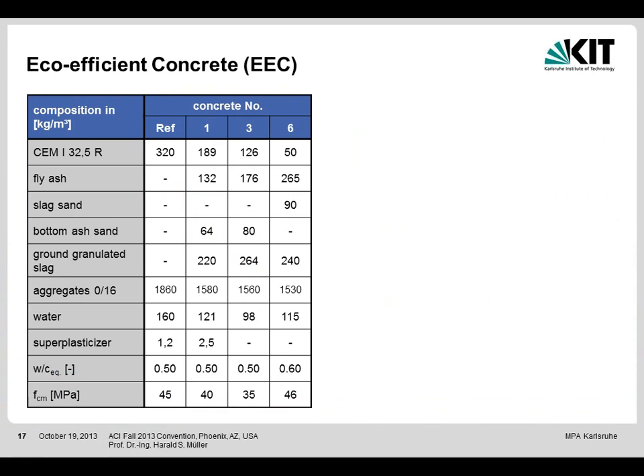Now you can replace more and more the Portland cement. You see, you reduce it to 1/3 and even to 1/6 here. You have to fill up with fly ash, with slag sand, bottom ash sand, and ground granulated slag. But you may end up finally with a similar compressive strength at the age of 28 days. This is actually no problem, even if you use only 50 kilogram of Portland cement.